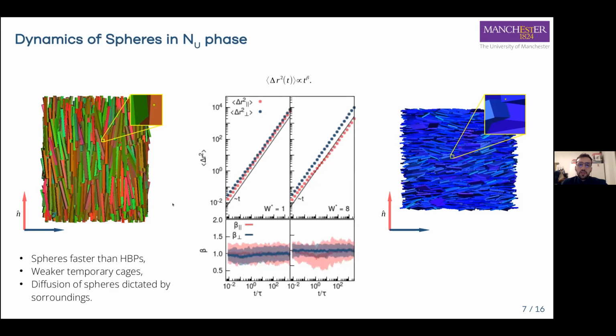And we also computed the dynamics. We investigated the dynamics of the hard spherical tracers that are diffusing in this mobile matrix of hard board-like particles, and their dynamics is guided by the orientation of the nematic phase, and they showed similar dynamics to the dynamics of hard board-like particles. So hard spheres move preferentially in the direction parallel to the nematic director in prolate nematics, and they move preferentially perpendicular to the nematic director in oblate nematic phases.